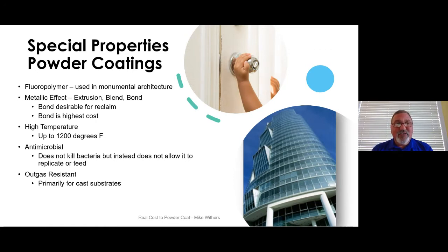So you create a base color, and then you dry blend in, or just thoroughly mix the metallic pigments in. That is a little bit more expensive than the extrusion process because you're having to do another process to produce it. And it's not as stable. So that product, if you're trying to reclaim, typically you would not try to reclaim blended products. In rare occasions where the metallic content is very, very low, and you're reclaiming through a cartridge system, you may be able to get away with it.